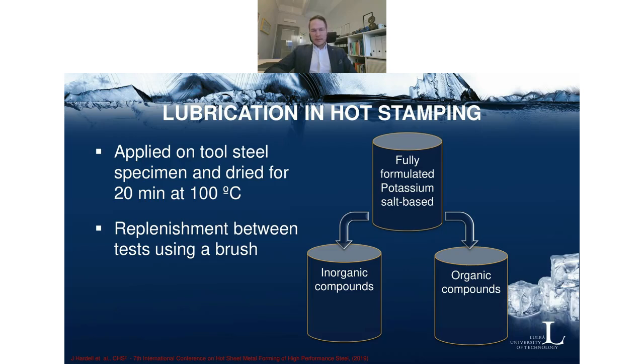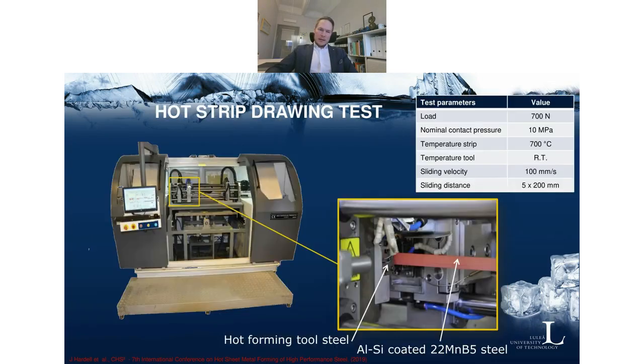So we apply the lubricant in this case on the tool as it would have been in reality. We dry it at 100 degrees in an oven, and then we also replenish lubricant. So we start with a dried layer of lubricant, and then we replenish with a brush between every experiment. For this purpose, we used a hot strip drawing test that we have in our laboratory.